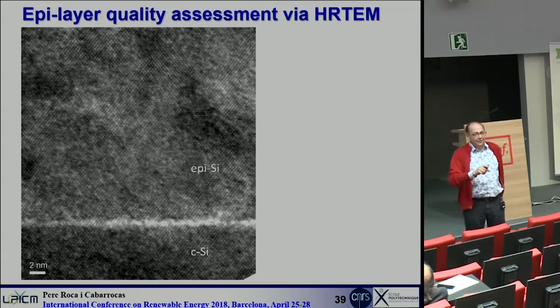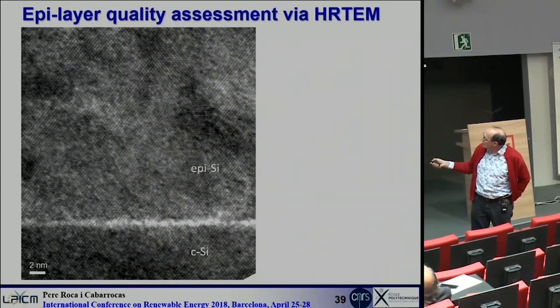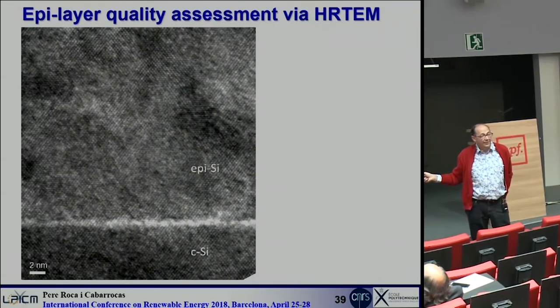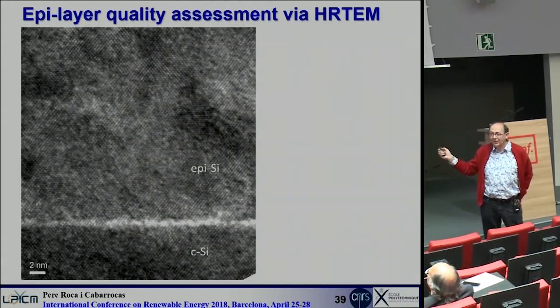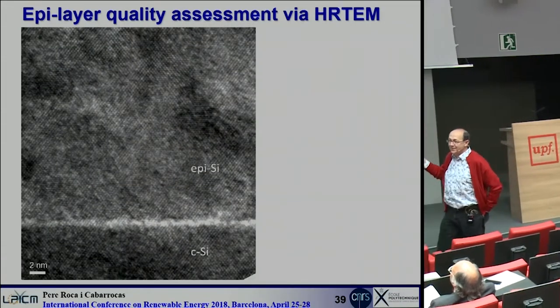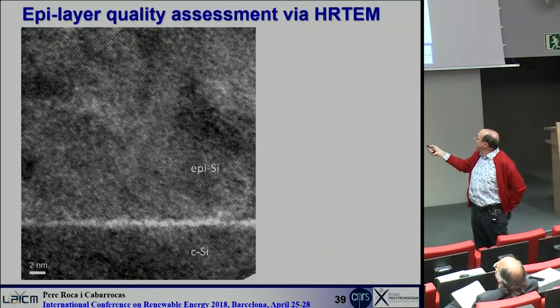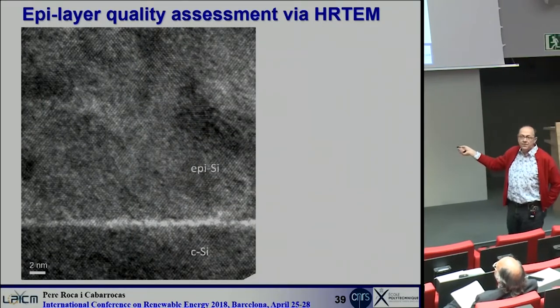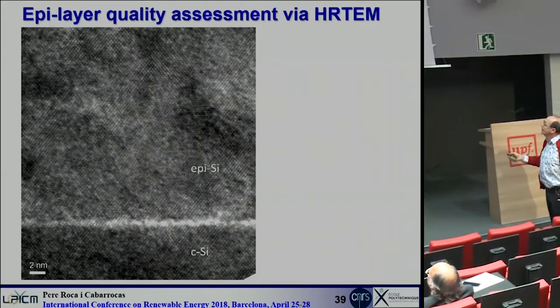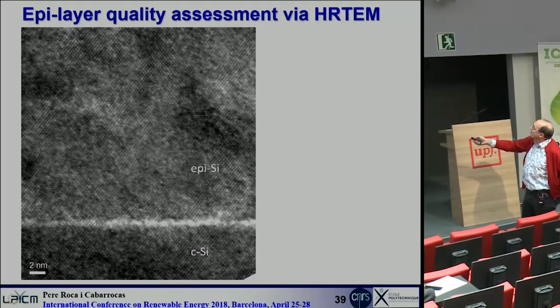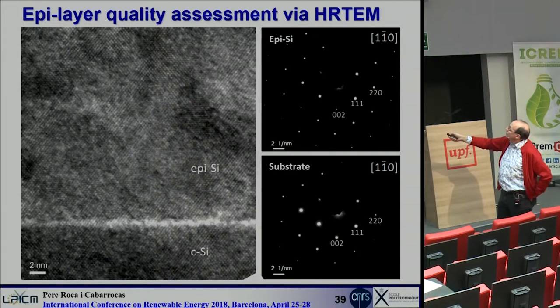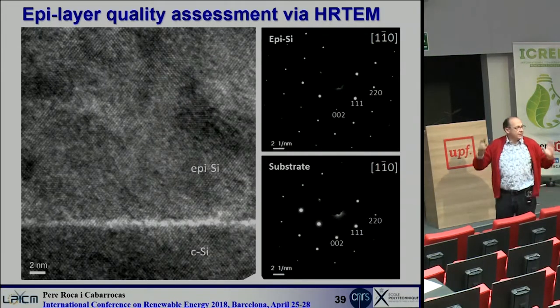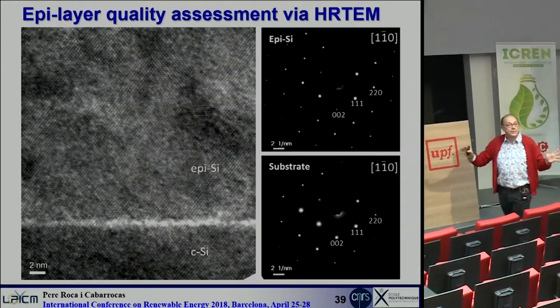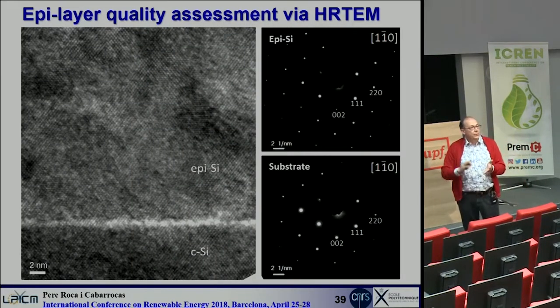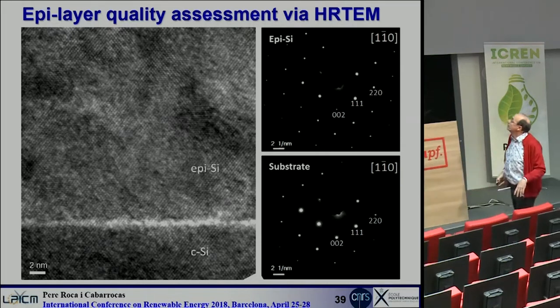For those who are still following, you will notice that here there is something. So it's not perfect. Who cares? In fact, we'll see that this can be an advantage. But for the time being, let's focus on this layer, electron diffraction of the epi layer and of the substrate. I have the same diffraction pattern. I am doing epitaxy, but I am not using high temperature nor ultra high vacuum. I am using a cheap process, 200 degrees.